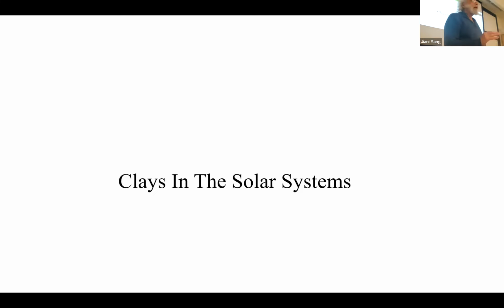So that is a very quick summary of what clays are and what their structure is. And the big thing is that in the smectite family of clays, you have this enormous variety, both at the tetrahedral layer and the octahedral layer. And that relates to how powerful they are as catalysts. Kaolinite is not a catalyst. It's not a good catalyst. Smectites are very good catalysts.